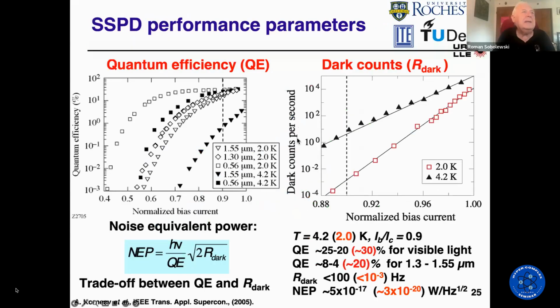Quantum efficiency, once again, is about 20–30%. You can see that at low temperature, if I go to high photon energies at 2 Kelvin, I have a saturation, and then a nice plateau, where I can reach the maximum quantum efficiency. Dark counts decrease exponentially with temperature. For my bias, which is this one, dark counts at 4 Kelvin are at about 1 hertz. But if I go to 2 Kelvin, they are essentially completely negligible.